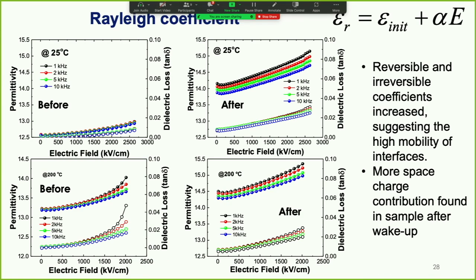And so we ask, is there really Rayleigh-like behavior in these materials? And the answer for the most part here is permittivity as a function of the amplitude of the electric field. Before I wake the material up, they are not really Rayleigh-like. They behave like there are no domain walls. Take the same material, run a polarization reversal process a couple times, and look what happens to the relative permittivity. It goes from about 12.5 to about 14. That's an enormous change in relative permittivity. I don't get to change intrinsic responses that much. It just doesn't happen. That happened because we built domain walls into the solid.